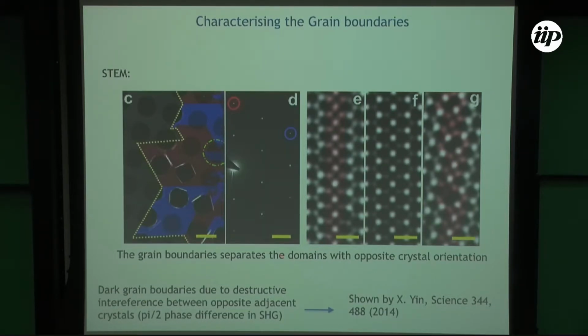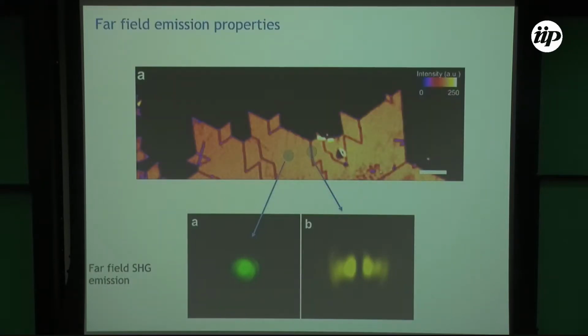Okay, so we really know that there's a grain boundary located in between the grains. What we have done is we put our input laser in the region where there is no grain boundary, and we detect the second harmonic emission, the far field. We are just seeing the shape of the light emitted by the sample. So this is the far field second harmonic emission. It's just a circular spot with a Gaussian shape because our input laser is also Gaussian.